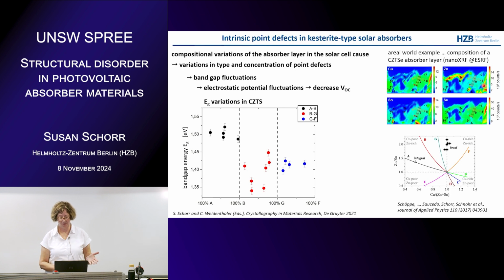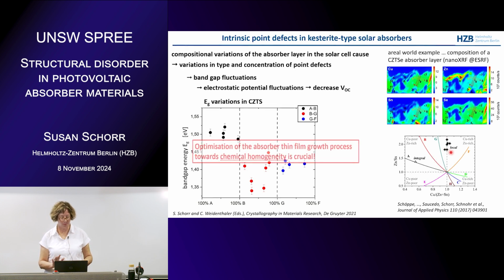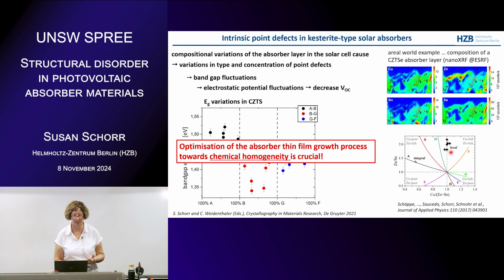For instance, if you measure the integral composition of your whole thin film by XRF, you will get this value and you will say, oh nice, I'm on the A-type line, great. But locally you have these compositions, for instance, and this is not very good. So that's why it's really important that you grow your absorber thin film as homogeneous as possible. So an optimization of the growth process towards chemical homogeneity is really important.